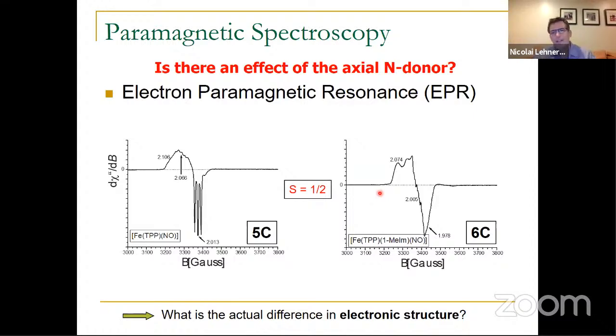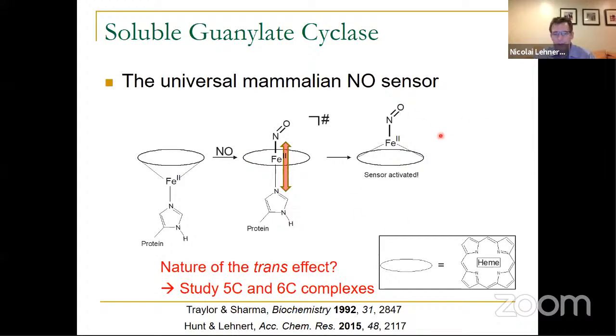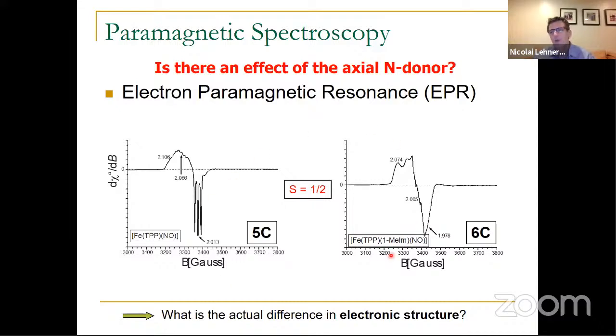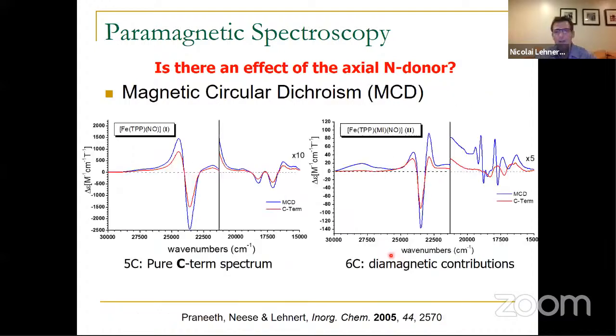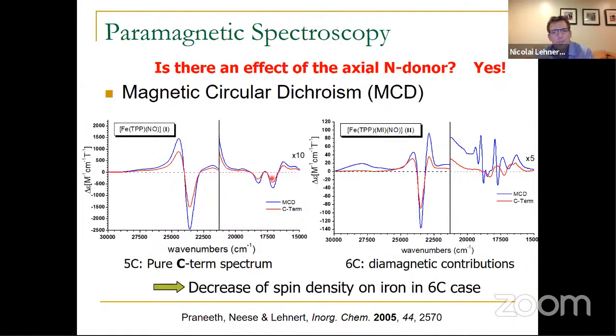but otherwise they look relatively similar, right? So one of the interesting questions then is, what is the difference in electronic structure, right? If we go back here, what is the difference in electronic structure between these 6 and 5 coordinate complexes? And yeah, the EPR spectra do not show a lot there in that regard. They look quite similar, right? We also did MCD spectroscopy, again, looking at these model complexes here. And in the MCD spectra, we see some differences. In the 5 coordinate complex, we essentially see a pure C-term spectrum, pure paramagnetic spectrum. But in the 6 coordinate case, we see these new signals coming up here. And these are essentially signals that indicate that the heme is becoming diamagnetic, right? And so the MCD data indicate that there is actually a difference between the 5 and 6 coordinate complex in terms of the distribution of the unpaired electron density. So that indicates that there is some difference here. But again, just looking at the spectra, it's hard to tell what it is.